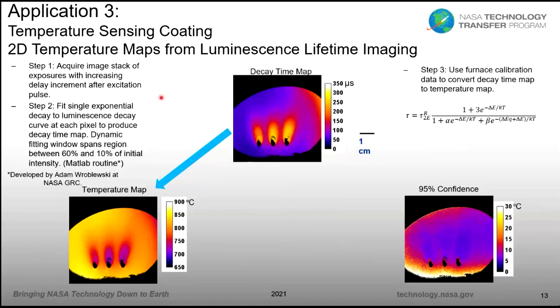So what we do then is fit a single exponential decay to the decay curve at each pixel in the stack. You can imagine if you go to one pixel in that stack, every exposure essentially covers a different part of the decay curve. That gives us our decay curve, and we can fit that to a single exponential. We do have to pick a window to span the range of delay times after the laser pulse, and we have to do it in an unbiased way. We developed a MATLAB routine to do that. Actually, it's Adam Wroblewski at NASA Glenn who did that, and it automatically does the window selection and then the fitting. So at each pixel, we start with a stack, and then we come up with a decay time value for every pixel in the stack.